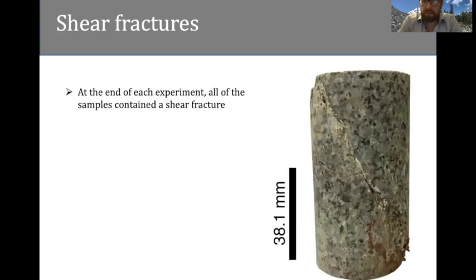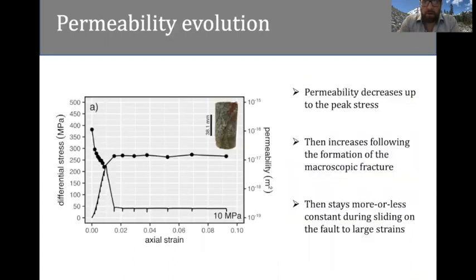So at the end of all 3 experiments, the samples, when they were retrieved from the machine and from the jacket, contained a macroscopic shear fracture like the one in the picture shown on the right-hand side here. So here's an example of the permeability data, which were collected using the steady state method during deformation, in which we stopped the loading of the sample. We measured the permeability using the steady state method, and then after we continued the deformation of the sample.